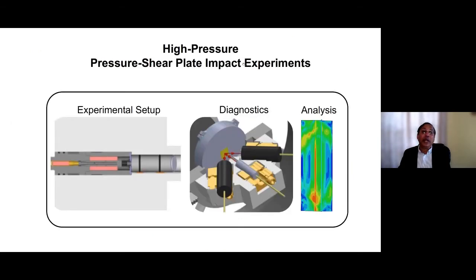As I mentioned, we want to use pressure-shear plate impact experiments, which is an elegant technique that has been very powerful in studying material behavior at high strain rates, but nominally low pressures, limited to about 10 gigapascals or so. We want to extend that beyond this regime. But there are numerous challenges associated with the technique: the experimental setup, the diagnostics, and how you analyze this problem when you exceed the Hugoniot elastic limit. These are the things I'm going to describe in the next few minutes before I show you the results on copper and magnesium.